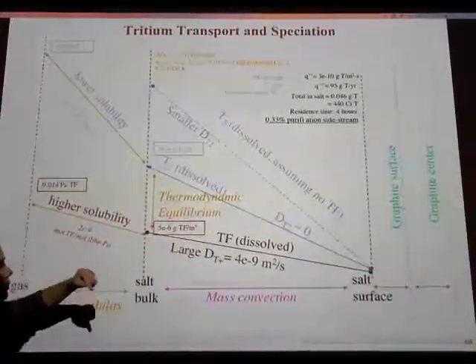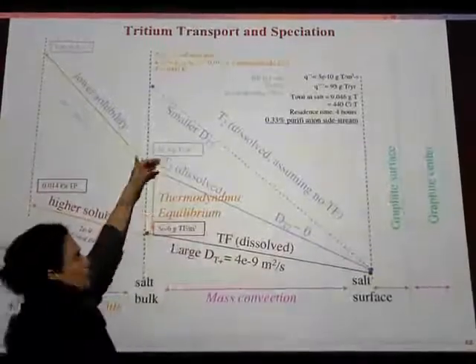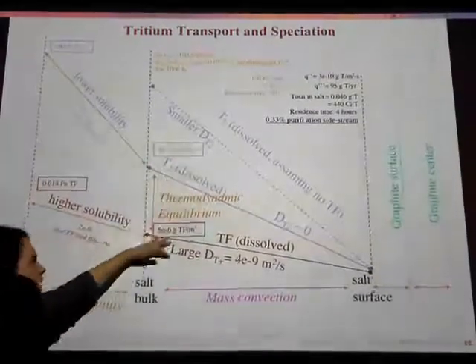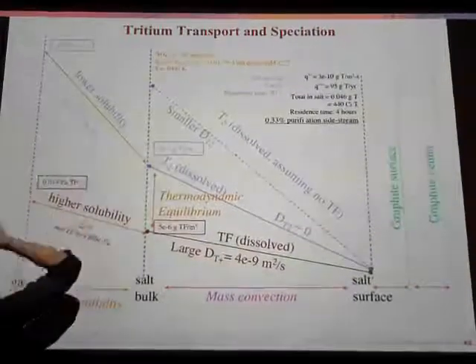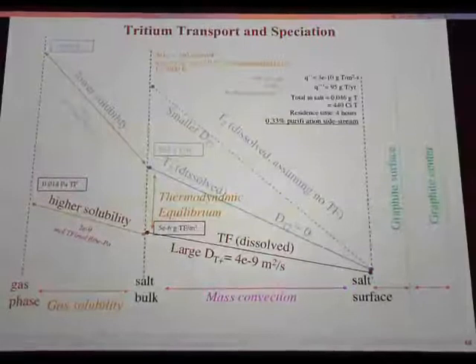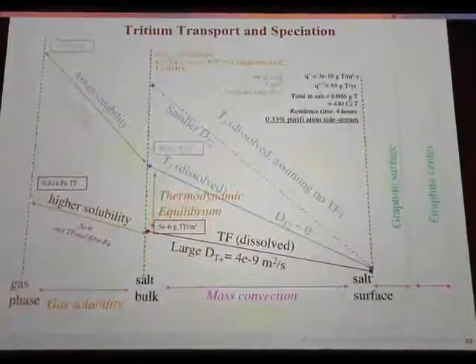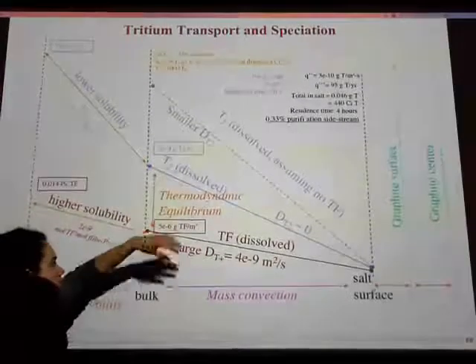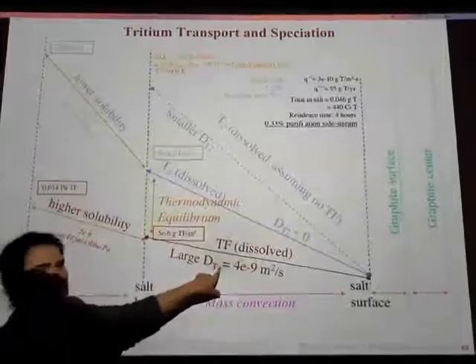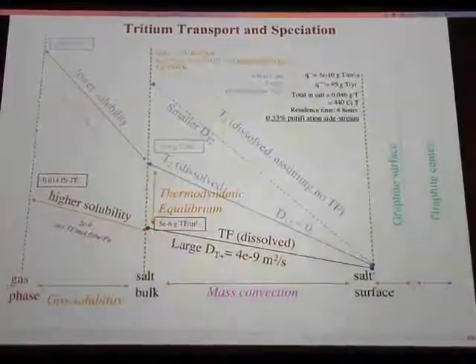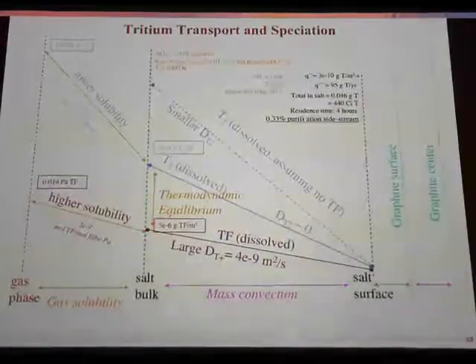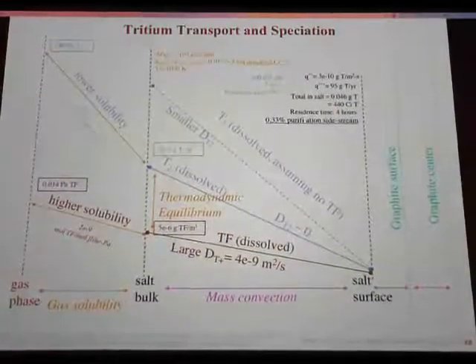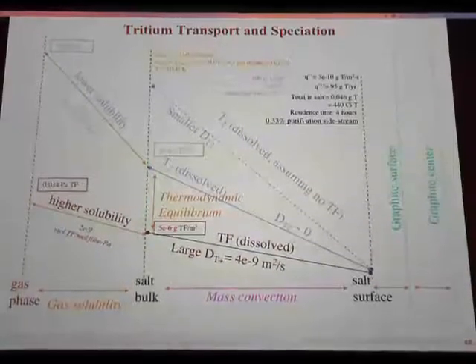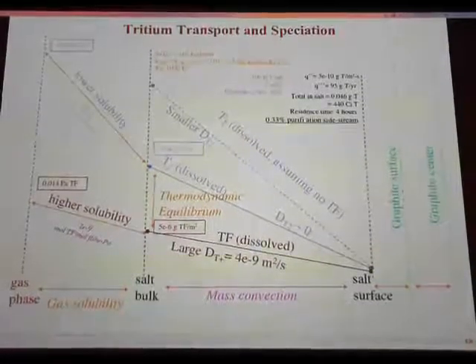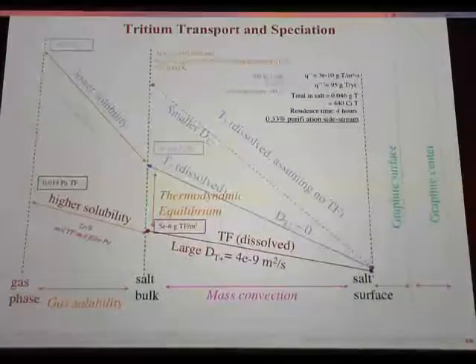And then you know that T plus is in thermodynamic equilibrium with T2. And so that thermodynamic equilibrium is set by how you do the chemistry control in your system so that you don't corrode your metallic alloys. So just like T2 can be in a 0 oxidation state, so it's T2 covalent, they share electrons, or in a +1 oxidation state, it's missing an electron. Same thing with metals. You can have chromium 2 plus or chromium 0. We like to keep chromium in a 0 state. So we like to keep it in our pipes, in our structural materials. If it goes into a 2 plus state, then it dissolves in the salt, and so we're corroding it.